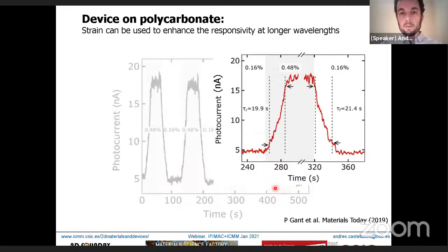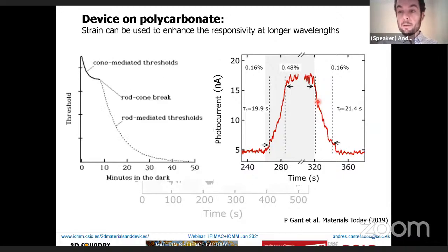If we zoom in on one of these cycles, we see that the time response of our devices is around 20 seconds—from the moment we turn on the heater until it reaches stabilization. That might look like a lot, but if we consider that we are trying to mimic adaptable photodetectors, one of the most common being the human eye, the human eye takes around 10 minutes to accommodate to different lighting conditions. In our case, our device will be able to adapt in just 20 seconds.